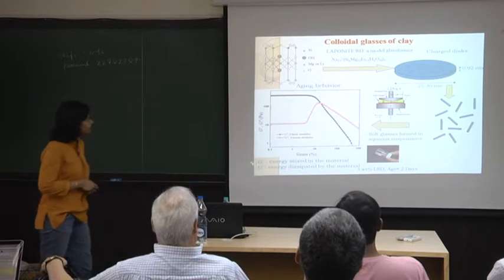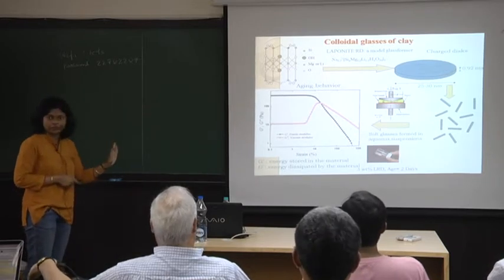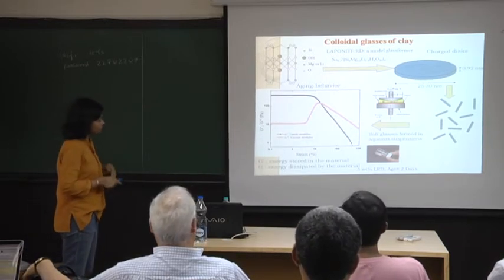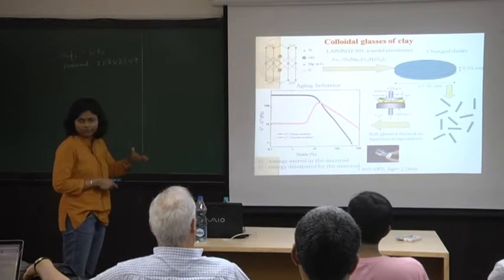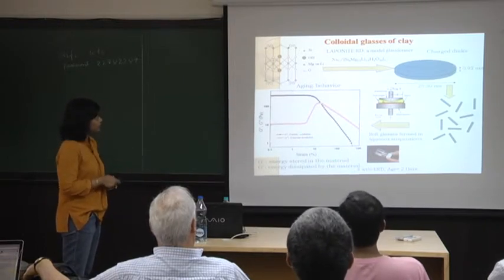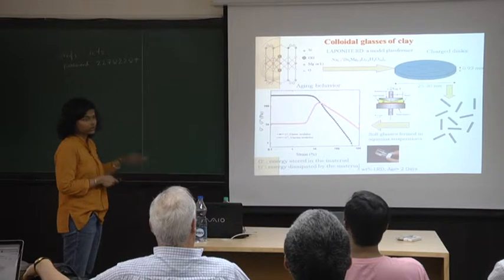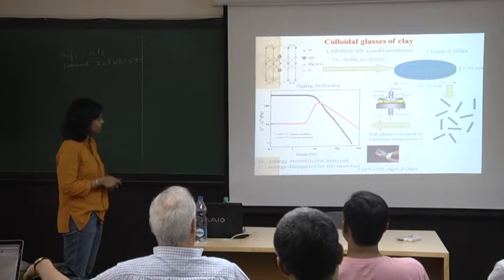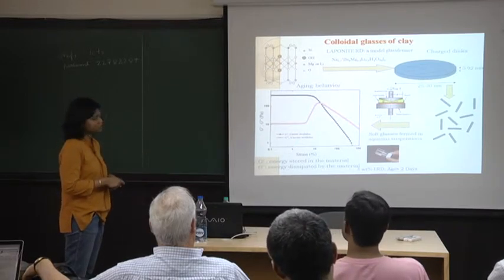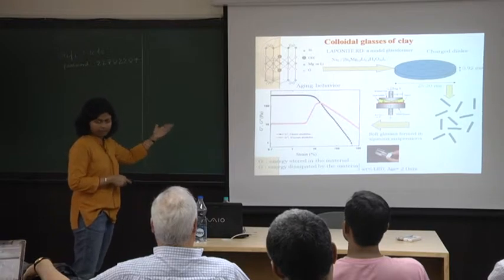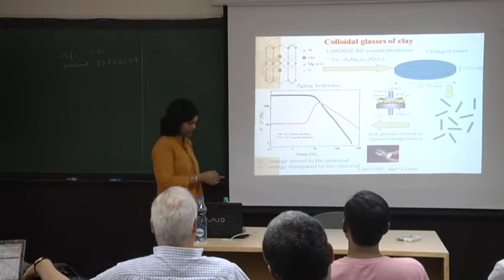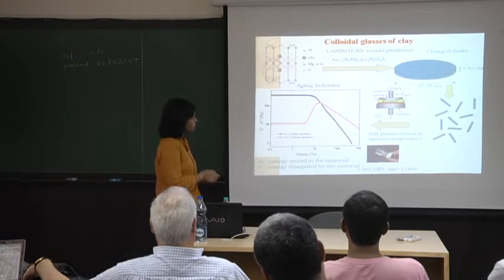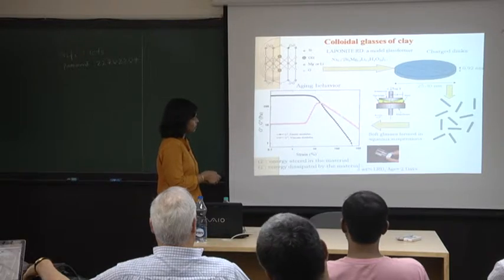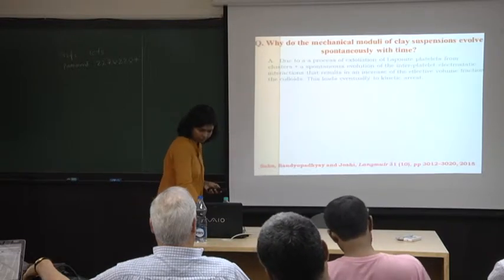This is the famous yielding curve. So here we've used a very small frequency. We do a step strain measurement, so we increase the strain. You can see that initially the elastic and viscous moduli are both pretty much constant. And after this, what you see here is a region of yielding. So the material is basically beginning to flow, as you can see from here, where the viscous modulus is higher than the elastic modulus.